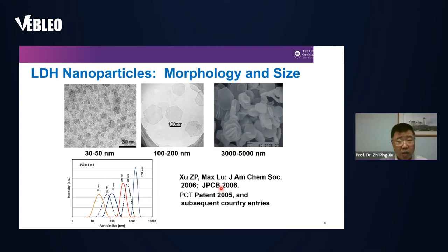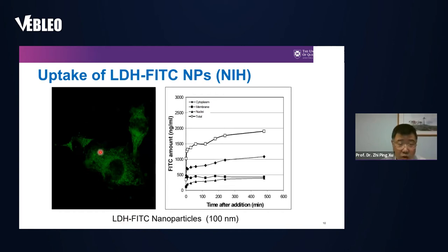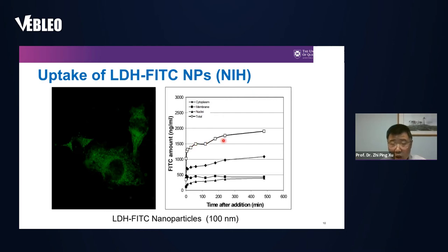These nanoparticles can be easily taken up by mammalian cells. We loaded FITC dye into LDH nanoparticles, and the green fluorescence shows the nanoparticles being taken up by the cells. Dynamic monitoring shows overall uptake increases very quickly in the first hour and extends up to eight hours. In the first hour, about 70–80% of the saturated uptake amount is achieved — this is a very rapid process.